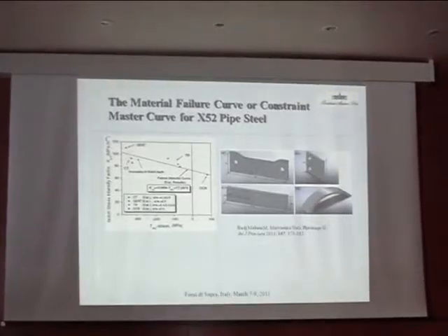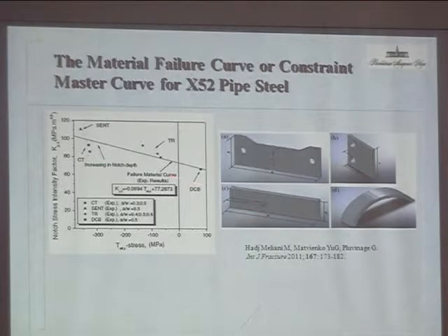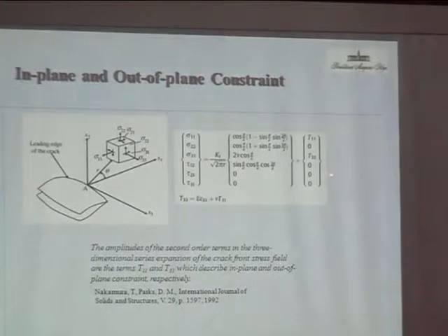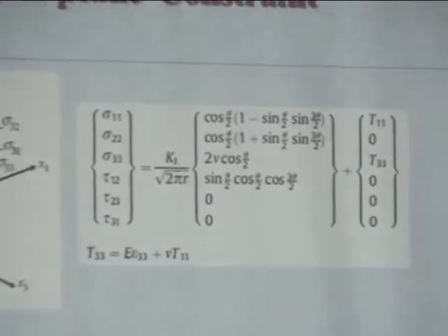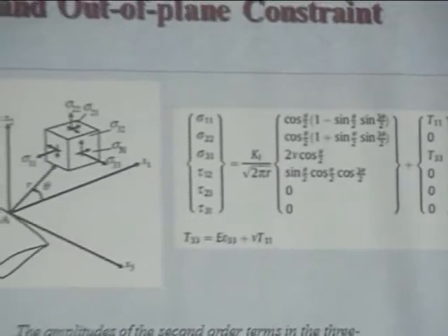You can see that notch fracture toughness, or critical notch stress intensity factor, against T-stress gives us some dependence for different types of specimens. So this is a good result, because in this case, if we have measured fracture toughness using some specimen, for example, a compact tension specimen, it will be possible to transfer this value to another kind of specimen configuration and type of loading. So it's a real way to construct some dependence which allows us the estimation of residual strength and lifetime of real engineering structures. But it's just a preliminary result, because we need to understand how to take into account the crack length, crack size, and so on. It's just for different kinds of specimens, but with the same crack length.